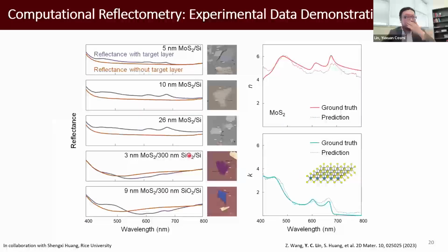After the training, we tested the system with our experimental data, so we can also see some level of prediction, but there's still some difference. The dashed line is the prediction, the solid line is the ground truth. So we verified, using the reflectometry, but we need to provide slightly more information. And using the neural network, we were able to still reconstruct the N and K information, but this system may not look that useful.